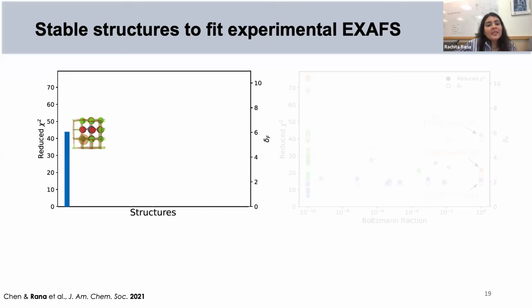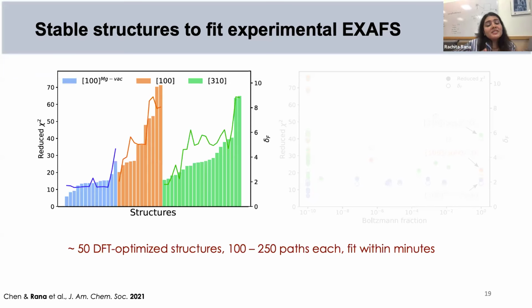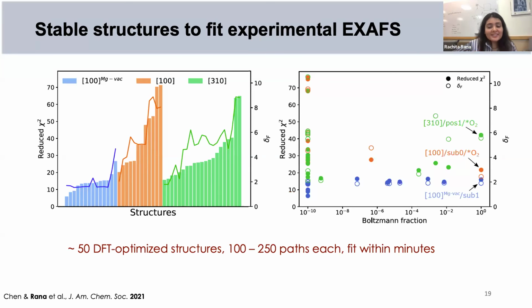experimental EXAFS fit. For instance, for this platinum on magnesium oxide system that was extremely homogeneous, we had about 50 DFT optimized structures in the database. And what you see here is the lower the value of reduced chi and delta r, the better the fit is in terms of EXAFS. And so these terrace sites with magnesium vacancy, which was very counterintuitive in the beginning to us, were some of the best fit structures.